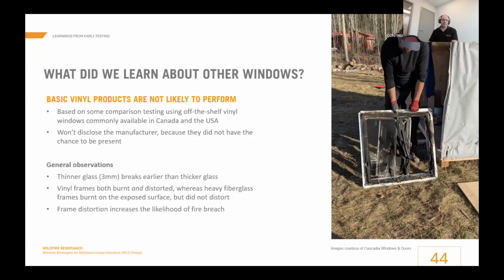We made some observations. Thinner glass, like 1/8 inch, breaks easier than thicker glass. We also noticed, and this was important, vinyl frames both burnt and distorted with the heat of the fire. Whereas the heavy fiberglass frames burnt on the exposed surface, like I showed you, but they didn't distort, because fiberglass doesn't melt or deform with heat. Thermoplastics do. And we observed that frame distortion increases the likelihood of a fire breach, because if you have a sash and a frame and they distort, they open up a gap between them where the fire can penetrate.